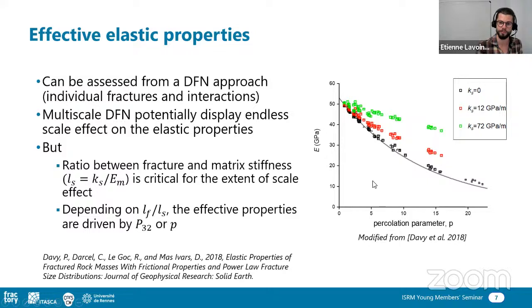And one of the biggest conclusions of that work was that multi-scale DFN potentially display endless scale effect on elastic property. So here on the graph, you can see the evolution of the Young modulus with percolation parameter characterizing the fracture density. And you can see that this decreases exponentially with percolation parameter if you consider that you have fractures that are frictionless. So here, Ks is the shear stiffness, meaning that you have no friction here. But as soon as you increase friction, the rock behaves differently.